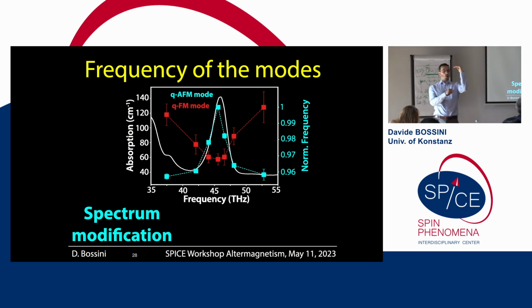We did take hematite, we did pump the 2-magnon mode, and changing the dispersion in the transient state, we did transform hematite into a different magnetic material. And please, take a look at how the frequencies have changed. The higher frequency mode blue shifts, while the lower frequency mode red shifts. That's the typical change in frequencies that you observe if the two modes are coupled, two degenerate modes.